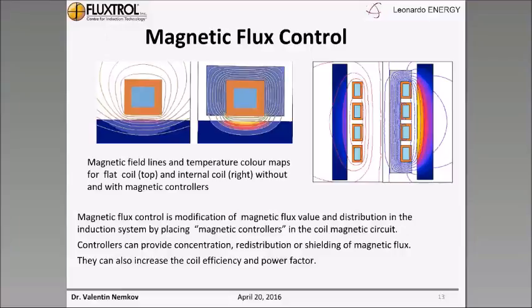These two pictures show you the magnetic field lines and the color map of temperature for the same coil current. You can see that with the concentrator we have a better shaped heating zone and much higher temperature than without. This phenomenon is especially important for internal induction coils, because in this case magnetic flux must return back inside of the coil with limited cross-section, and the presence of magnetic controllers can significantly influence and improve the heating.